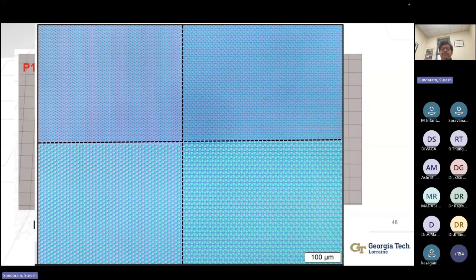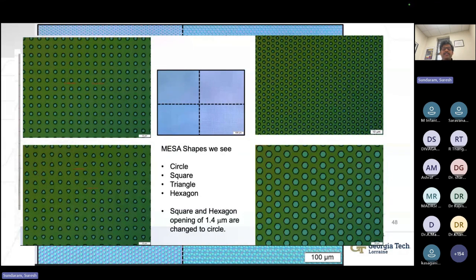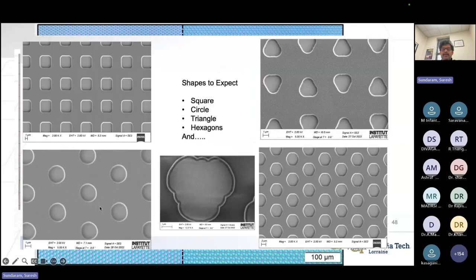These are the optical microscope images showing the holes in the silicon dioxide. Holes are in blue, and the gray area is silicon dioxide. Here you have circular, hexagon, triangular and square patterns. You can see it clearly in the higher magnification images: hexagon, circular, square, and triangle. These are SEM images. You can see it clearly: hexagon, triangle, square, and circular. Some of them have anomalies, but for triangle, we are getting something like this because of the photo mask in some of the regions. But most of the areas are really well defined. The feature size is 1.4 micron; let's say we aimed for 1 micron, we get close to 1.4 micron.